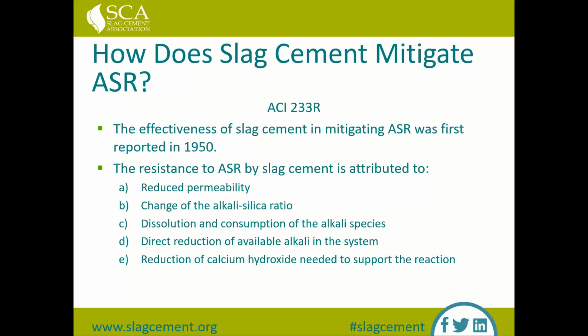Next, we've got listed 5 factors of how slag helps to reduce ASR damage. The first one is the reduced permeability. I think that's a big factor with the durability benefits of all different types of attack associated with the use of slag. As Keith showed in the one diagram, the reduced permeability in systems containing both Portland and slag - you've got the smaller and less interconnected void structure leads to the reduced permeability that really helps with durability all around in concrete containing slag.